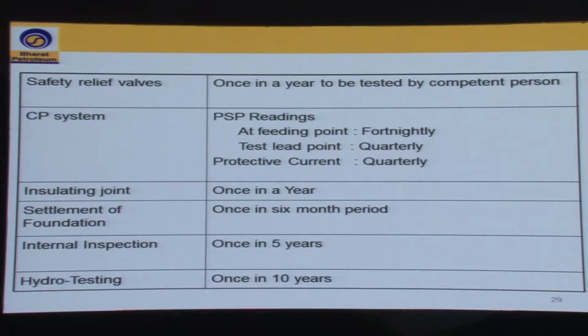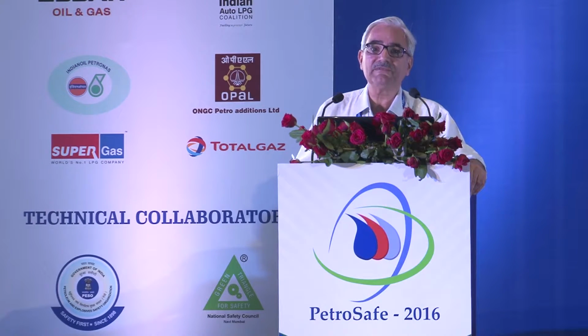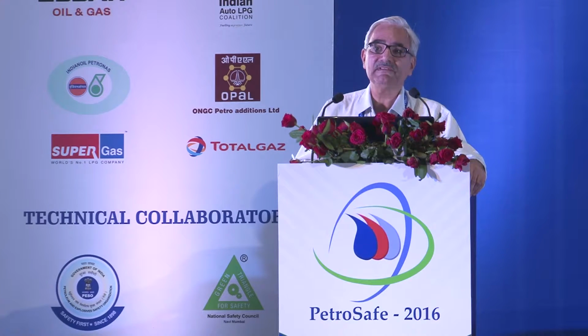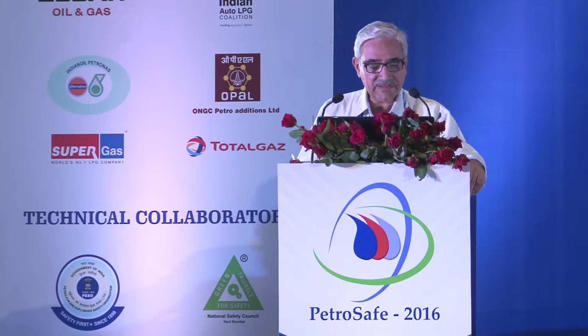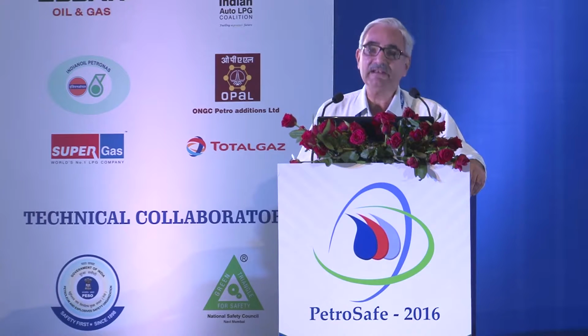Third thing, the cathodic protection system which is provided, mainly the PSP readings, these are the frequency which has been given as per the OISD guidelines. OISD 150 gives the guidelines. Then one more important point is, since it is a large vessel and a huge weight is there, the settlement is very important. This has to be measured periodically. Hydro testing of the vessel as per the OISD requirement is once in 10 years, and internal inspection is once in 5 years.